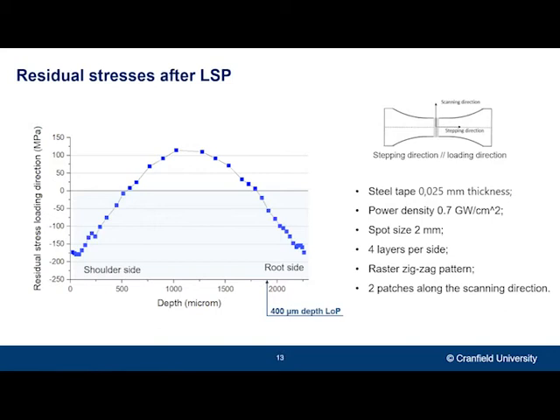The surface stress is also compressive, which is important to try to prevent crack initiation from the irregular surface that is characteristic of the friction stir weld. And the peak tensile stress was about 100 megapascal, which is quite significant. However, the good news is that that stress is in a non-critical location, basically away from these potential lack of penetration defects.